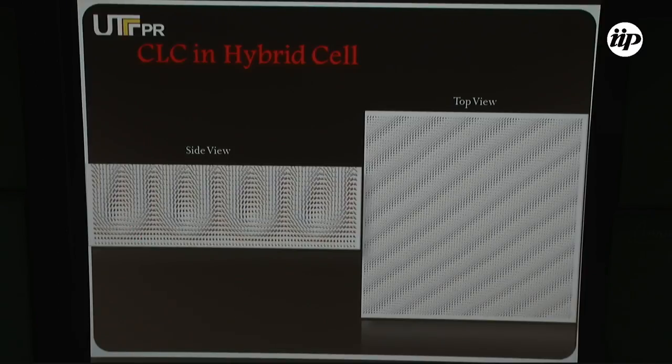Here we have those. I mean, there are defects, but they are cholesteric defects, like no core, those lambda lines. Yeah, but no core lines. Maybe it depends on the substrate. Yeah, but in this simulation we have weak anchoring here. That's why it looks like this. If it's stronger, the whole thing is pushed down to the bulk. And in this case, I don't remember if it has a defect here or not.